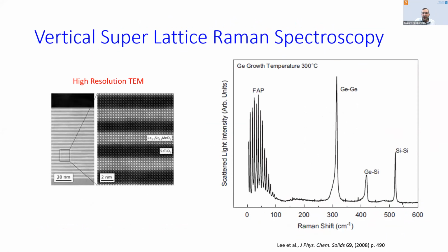LFR is also very sensitive, not only for size characterization on the nanoscale, but also for characterizing layered structures. These are some very beautiful MBE grown superlattices made out of semiconductors. And you can see that when you look at the low frequency Raman, if you have a silicon germanium superlattice, not only do you see the bonds of silicon germanium or silicon, but you actually see a whole manifold of states called the folded acoustic phonon modes, which are correlated to the thicknesses of the nanostructure. So we can learn a lot about the nanostructure from the low frequency Raman regime.